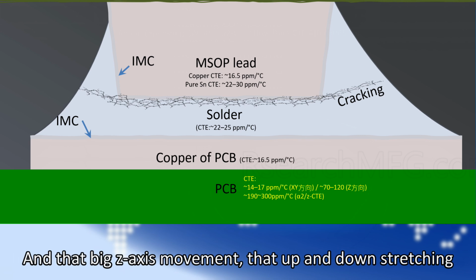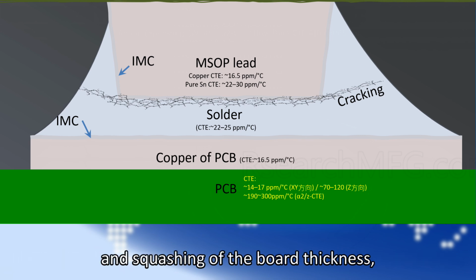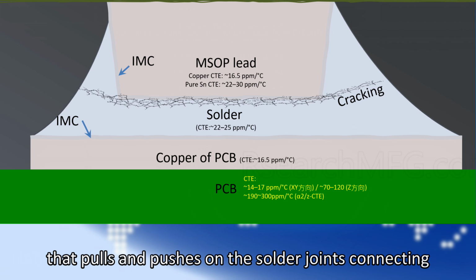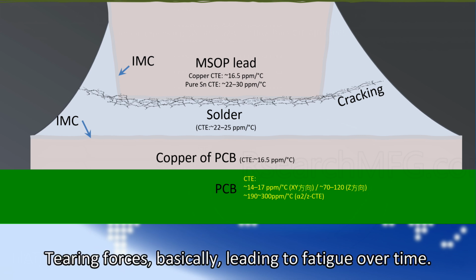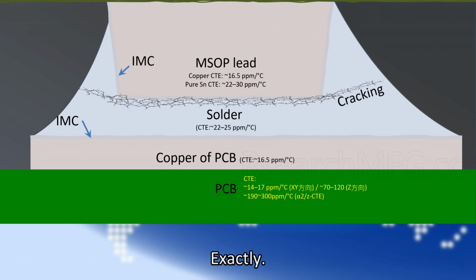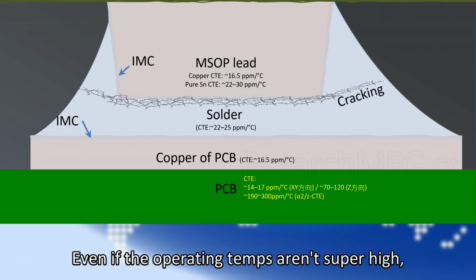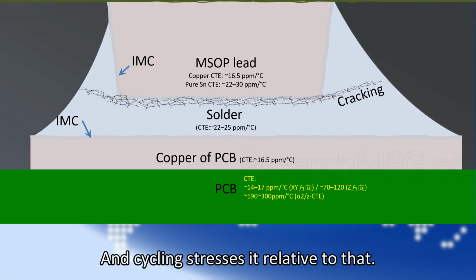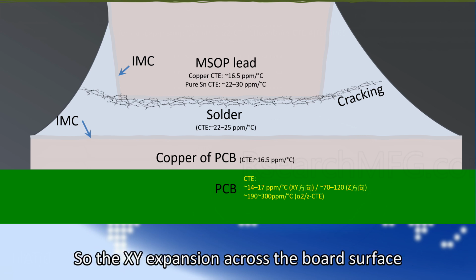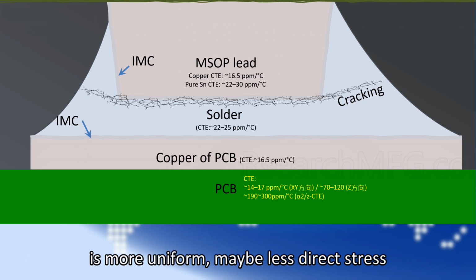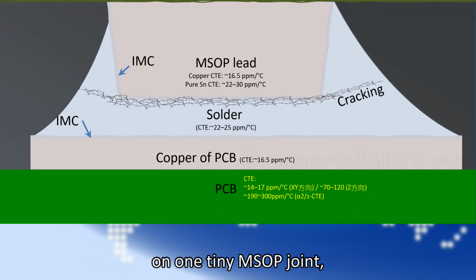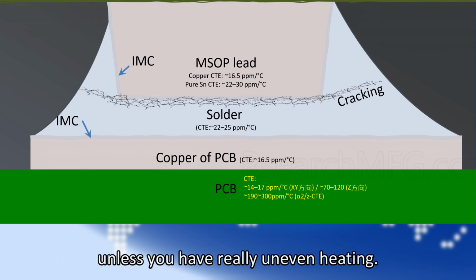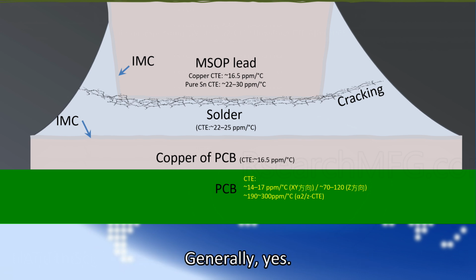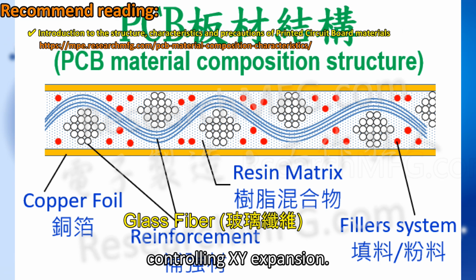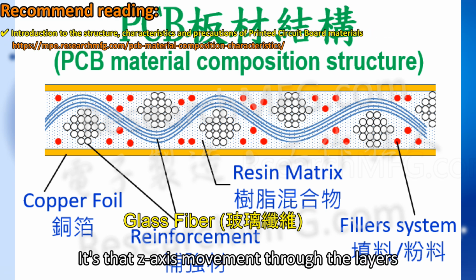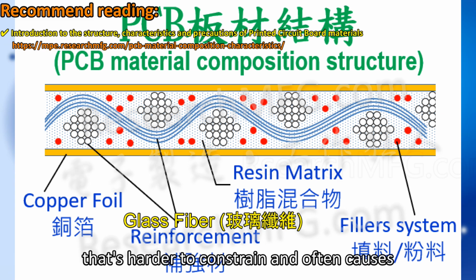And that big Z-axis movement, that up and down stretching and squashing of the board thickness, pulls and pushes on the solder joints connecting the components. Tearing forces, basically, leading to fatigue over time. Exactly. Even if the operating temps aren't super high, the board remembers that high temp reflow state, and cycling stresses it relative to that. So the XY expansion across the board surface is more uniform, maybe less direct stress on one tiny MSOP joint, unless you have really uneven heating. Generally, yes. The glass fibers in the FR4 do a decent job controlling XY expansion. It's that Z-axis movement through the layers that's harder to constrain and often causes more trouble for the joints.